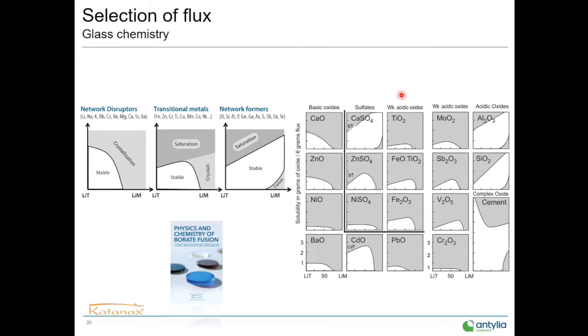On this slide, we have theoretical values of solubility of different elements in different types of flux. For each element here, you have lithium tetraborate on the left side, lithium metaborate on the right side, and you can see how many grams of sample you can digest in a fixed amount of 6 grams of flux. If we take silica, which is very popular, and use pure lithium tetraborate, you can not digest really more than maybe 0.6 grams of sample in 6 grams of flux.